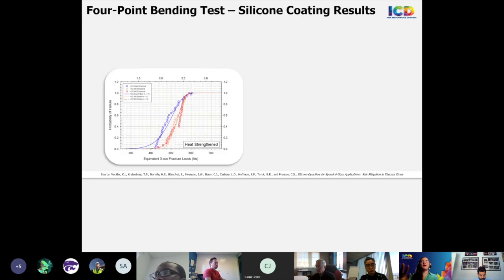First, we're just looking at the results for heat strengthened glass. And again, we have a similar testing arrangement. And this was also tested to that same ASTM standard that frit was tested. And we have the probability of breakage on the vertical scale against the equivalent stress on the horizontal scale. And you hit 100% probability for the clear, which is represented by the blue line at around 600 pounds per square inch.